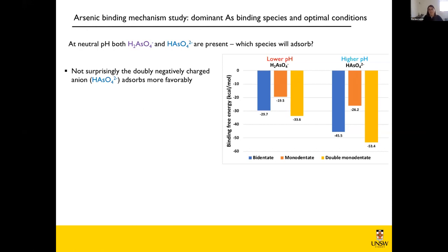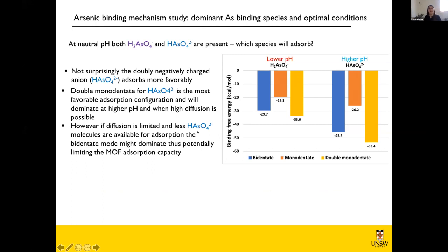But the other interesting thing to observe here is that, if we're thinking about a high diffusion regime with a lot of molecules around, we can again expect that the double monodentate will dominate here. But the problem comes in case we have a lower diffusion. In that case, we can only have one molecule binding at a time.